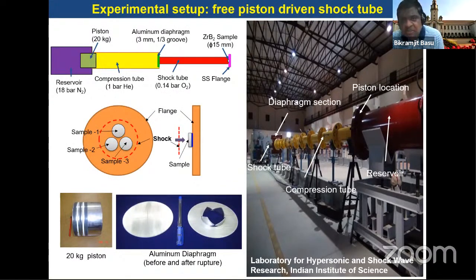This is the third and last one as far as the performance qualifying tests are concerned, and this is what we have done at our Center of Excellence in Hypersonics at the Department of Aerospace Engineering of the Indian Institute of Science, and we have used a free piston driven shock tube. Essentially, you pull this 20 kg steel piston in the reservoir. Once you release this piston, it will burst this aluminum diaphragm, and after rupture, the shock wave travels through this shock tube and then impinges on the zirconium diboride or niobium diboride, whichever you keep at this end of the sample.